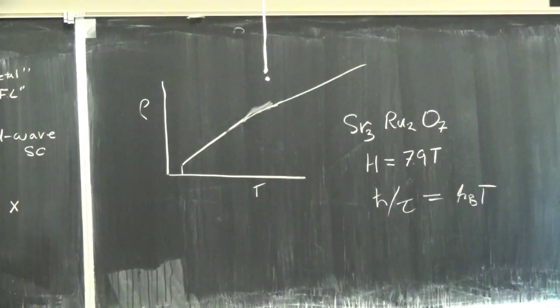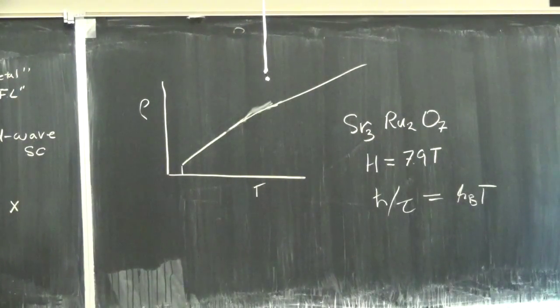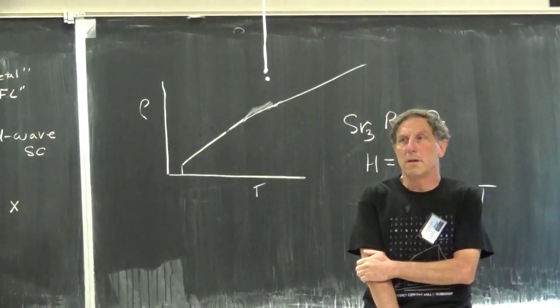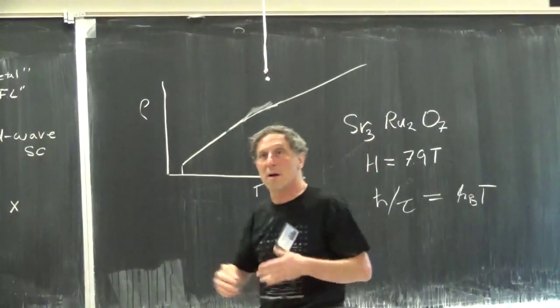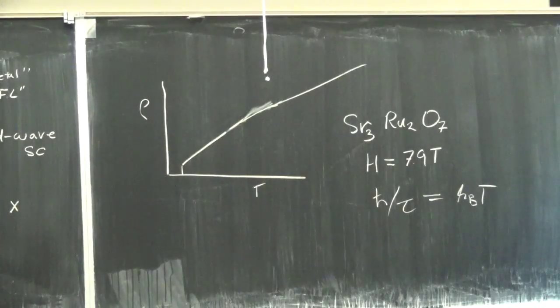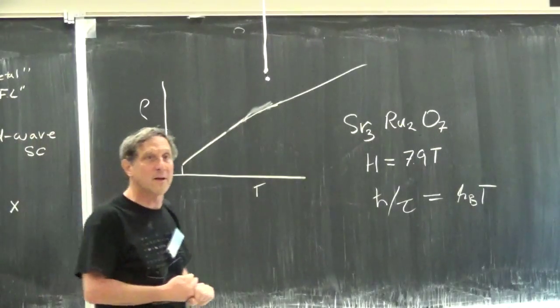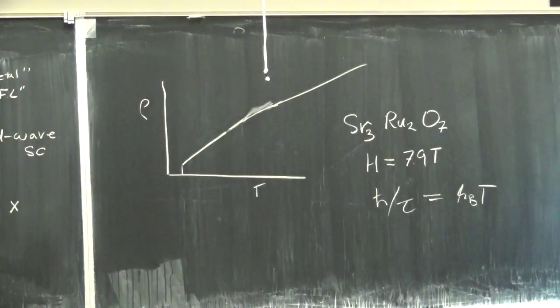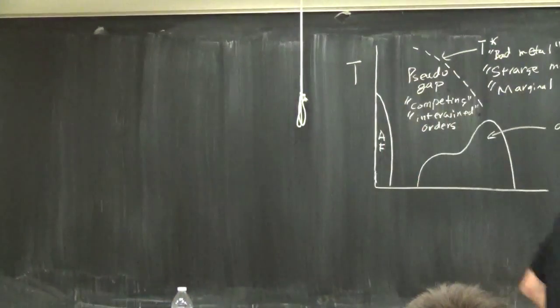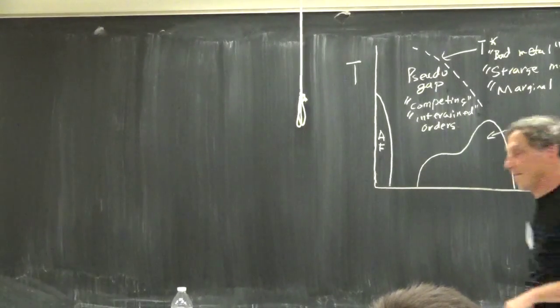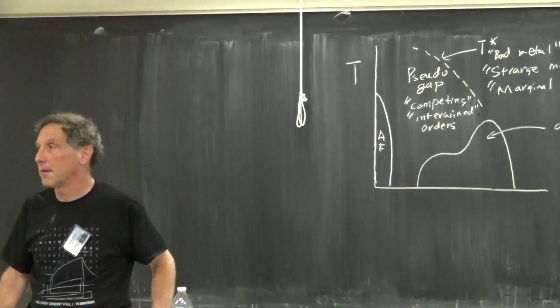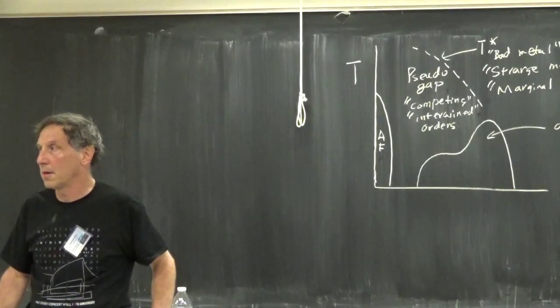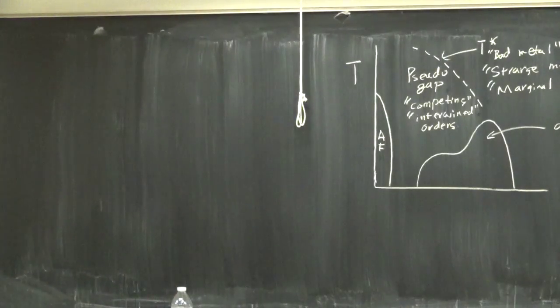Are the ranges in parameter space over which this kind of linear behavior is seen in other examples also looking like fans? In strontium ruthenate 327 this T-linear behavior is magnetic-field independent, so at low temperatures you're tuning yourself to some quantum critical point with field; at high temperatures you see this. That doesn't necessarily answer your question, but if it's a fan it's a damn broad fan.